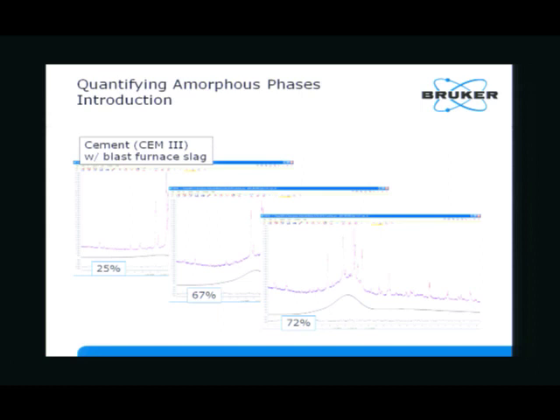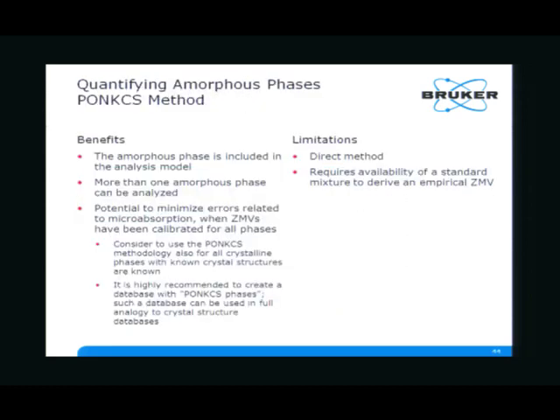What you can always do is, if you have a pattern you assume represents your amorphous phase, try different methods: put some spiking phases in it, work out the amorphous content, use the external standard method on top of it. That's already something for the conclusions: never rely only on one of these methods. They are so easily combined, and if all these methods are in sort of agreement you may be on the safe side. We will go through the PONKCS method in a step-by-step tutorial workshop on Friday, so if you want to learn how this is actually done, you're very welcome to join us.